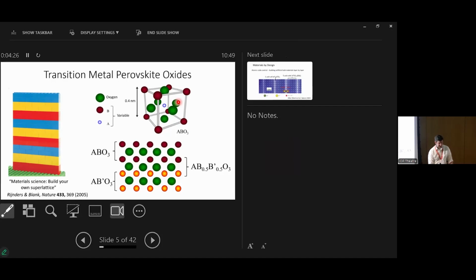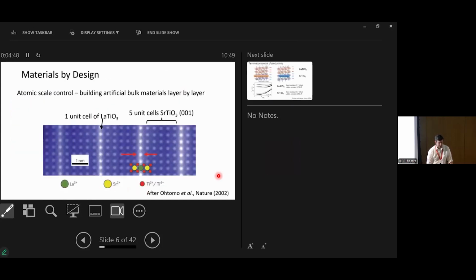In the simplest case, you take 2 materials, where A is some element, B is some element, and O is oxygen. All we've done here is switch the B element, so B to B prime. And if you stack these materials together, the interface is a brand new material with this chemical composition. This may not exist in nature, and it can give you new physics. So that's the idea. Can you do it?